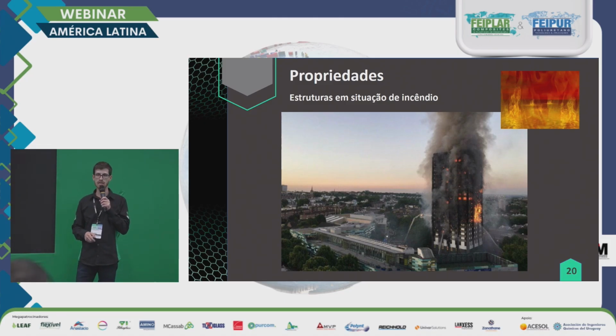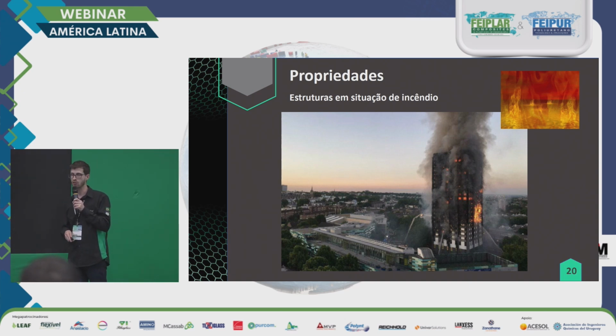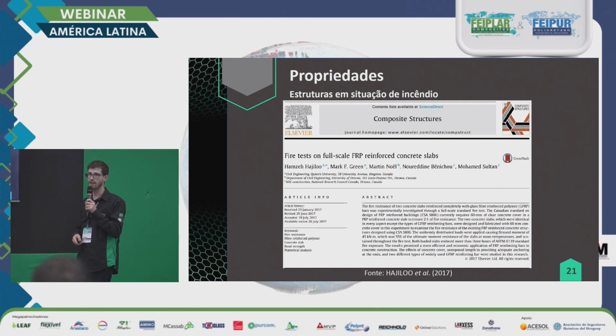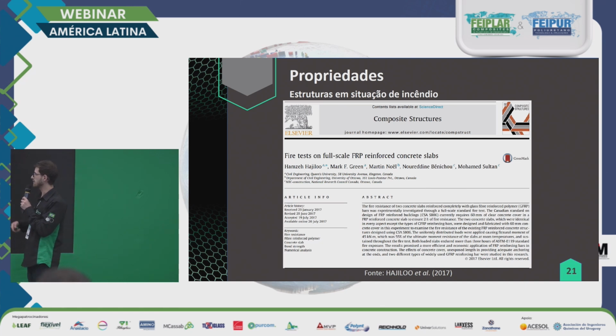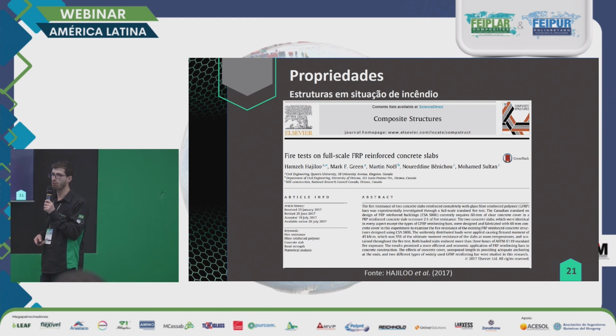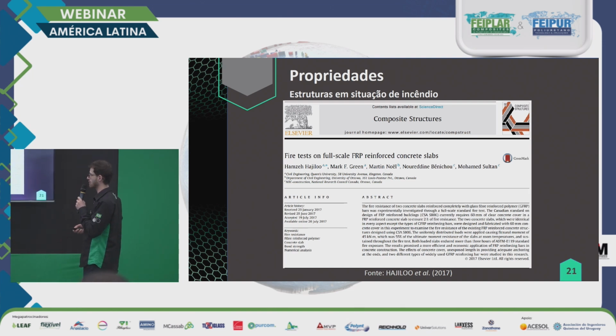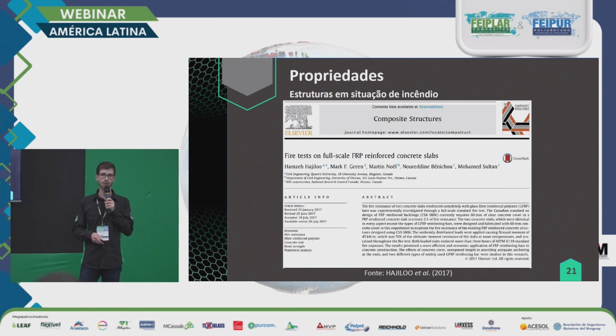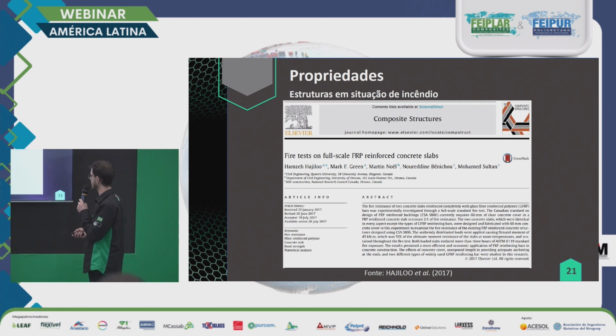As to the behavior of this material within a structure that may catch fire, this has been tested at a Canadian university, and this article has been published showing the findings of this test, in the Composite Structures Journal. And you can see the summary on the screen. They've used the Canadian standard for structural elements with fiber reinforced rebars and meshes, CSA S806, which was updated in 2021 for the last time. And here you can see what they tested.